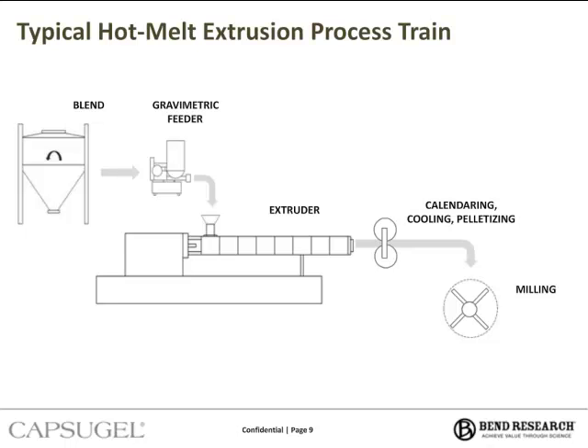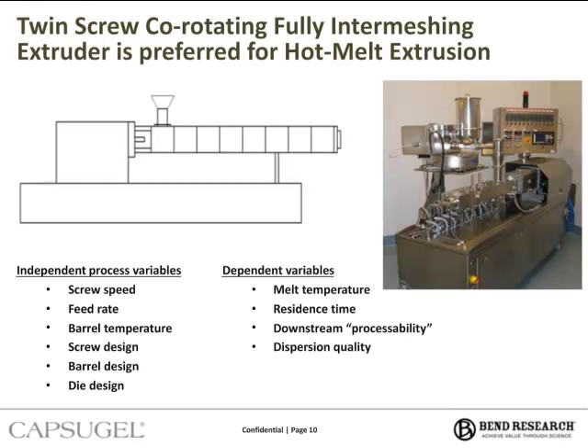Now, at the heart of this process train is the extruder. And a twin-screw co-rotating fully intermeshing extruder is preferred for hot melt extrusion. And this is simply because it has better mixing than a single screw or non-intermeshing extruder. The twin screw extruder consists of 2 rotating screws and a segmented barrel. Some of the process parameters are listed on this slide.